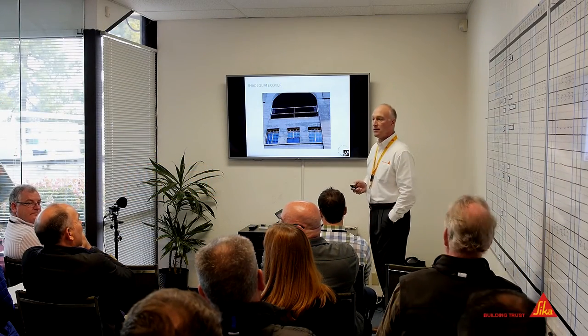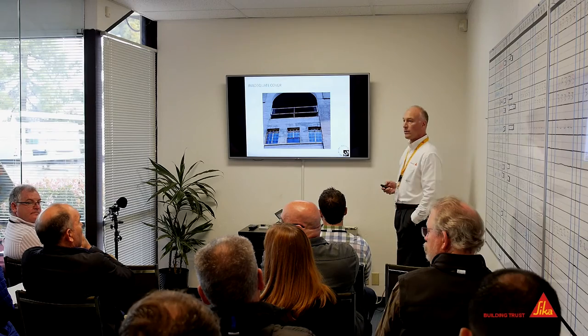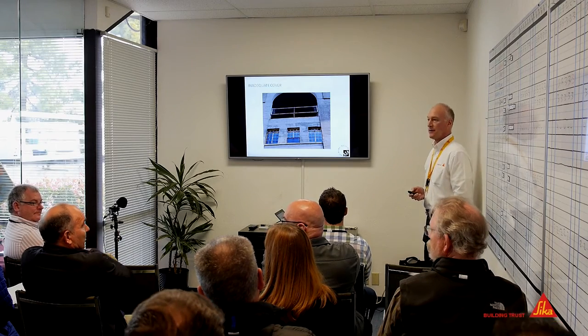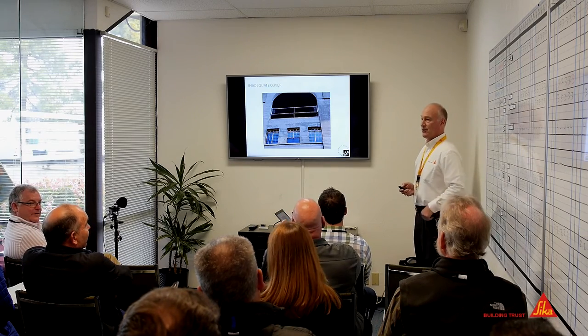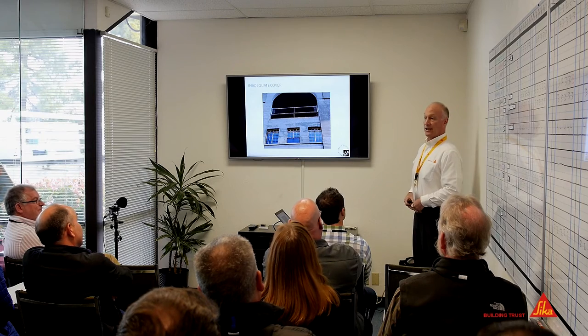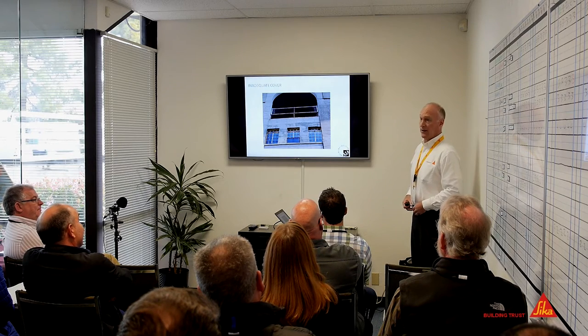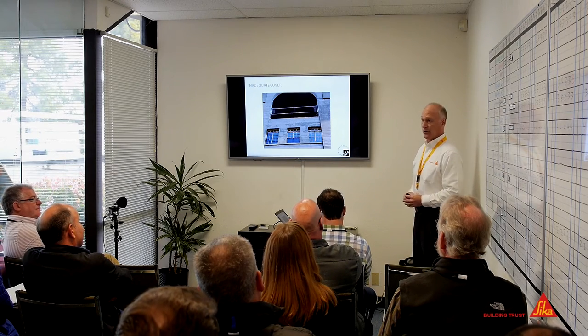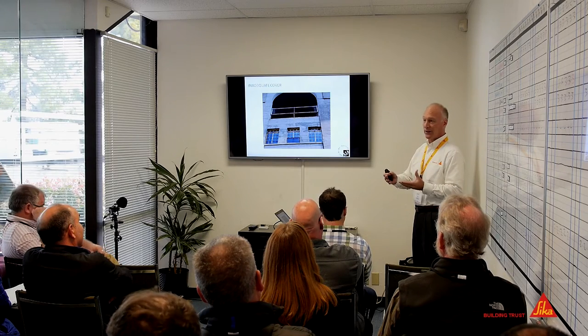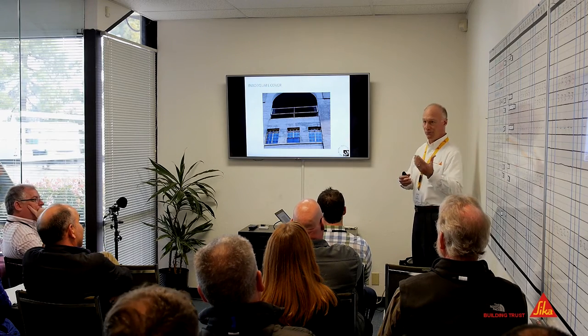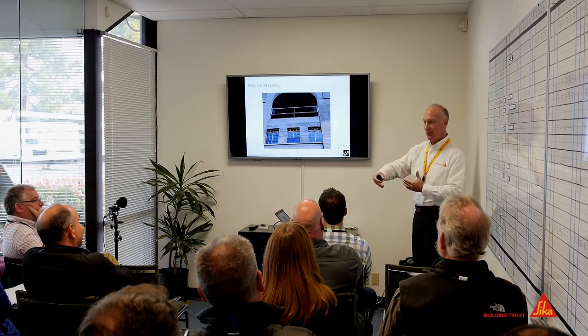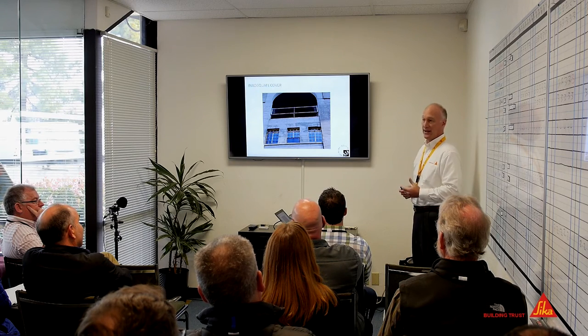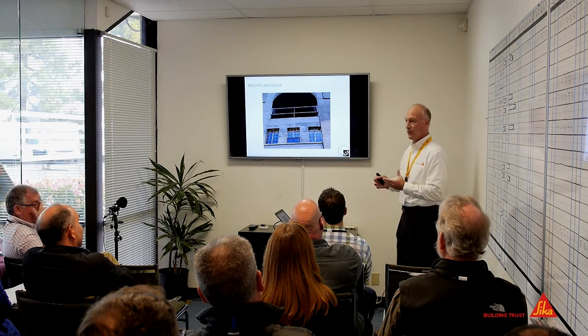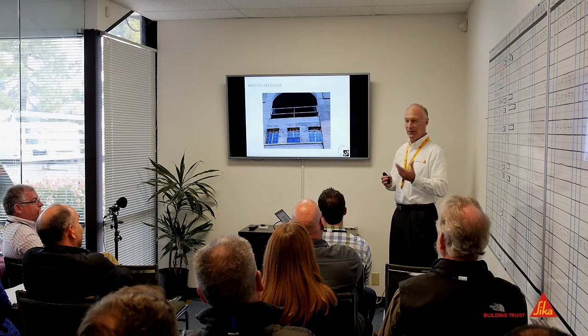Another accelerator that we discovered is bad aggregate, pyrites in your aggregate, which pops stuff off too. Sometimes we get alkali silica reaction, and aggregates could be another source of causing the spalling, which then leads to steel being exposed and ingress of other aggressive chemicals. So it's really important to understand what the root cause is before you devise the fix.